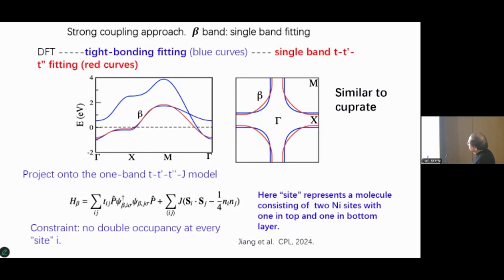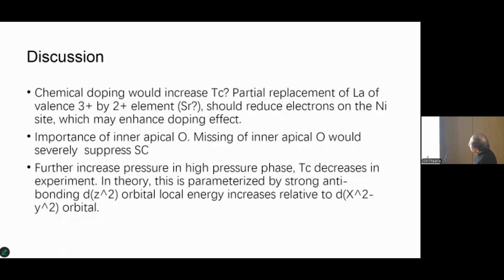That simplified version was taken by us, I think published in Chinese Physics Letters. So more complicated things, instead of showing you a lot of parameters which we are still working on, I just like to make a few comments. Chemical doping would increase Tc experimentally. The partial replacement of lanthanum of valence 3+ by a 2+ element should reduce electrons on the nickel side, which may enhance the doping effect to increase Tc. So that is a possibility we would suggest experimental colleagues do.